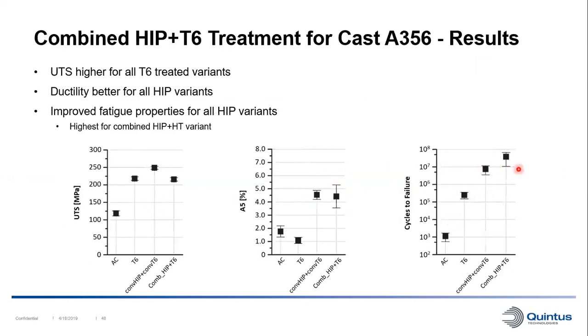Also, as expected, we see better fatigue properties for the variants that have been heat-treated, and also the hipped variants here are higher than the just heat-treated variant. Interesting here was that we actually got better fatigue properties of the combined hip and heat treatment variant, even though it had a little bit lower strength than the conventional hip and heat treat variant.